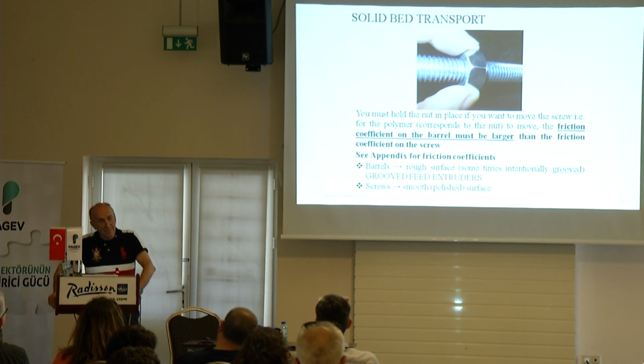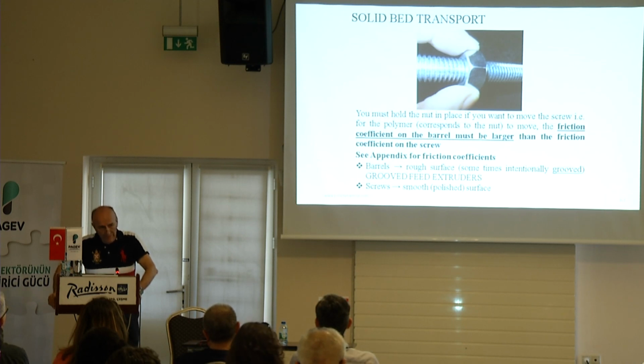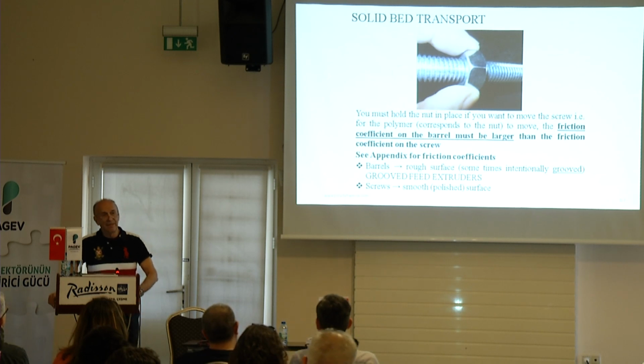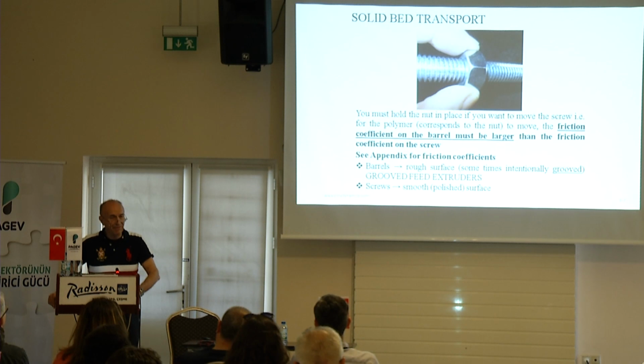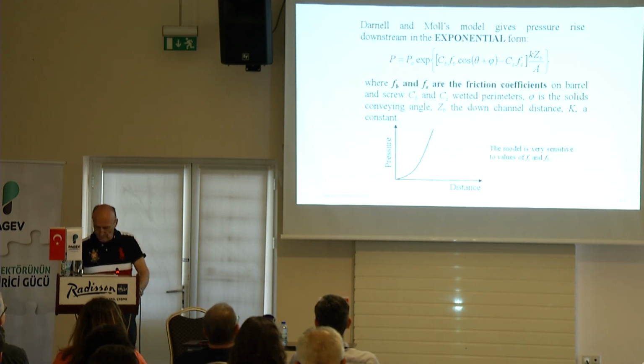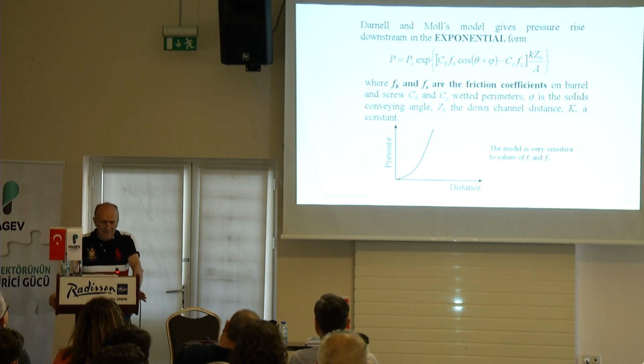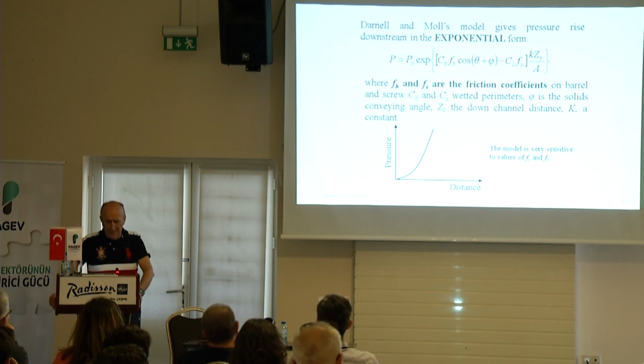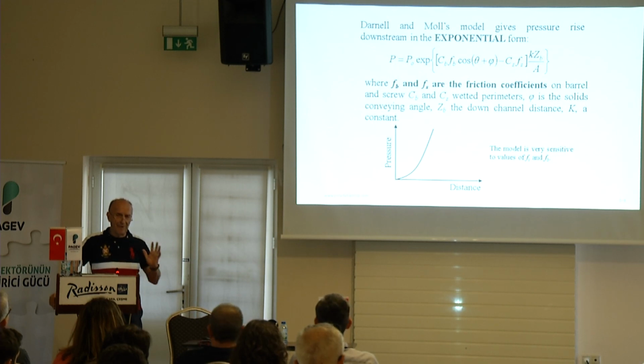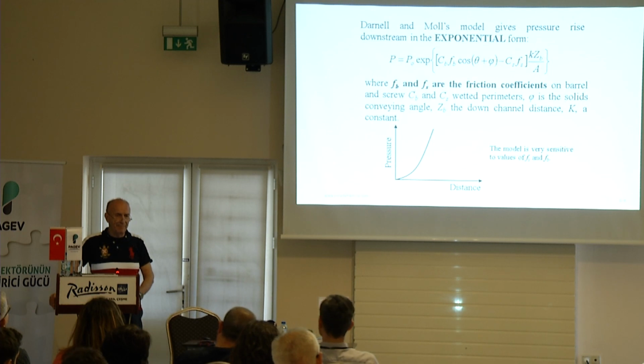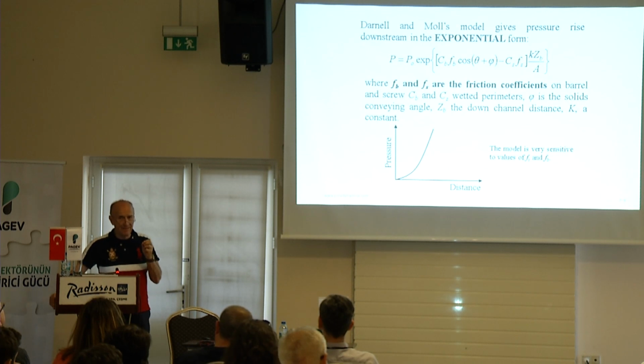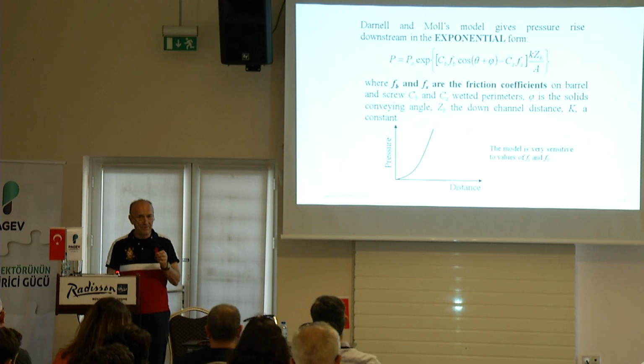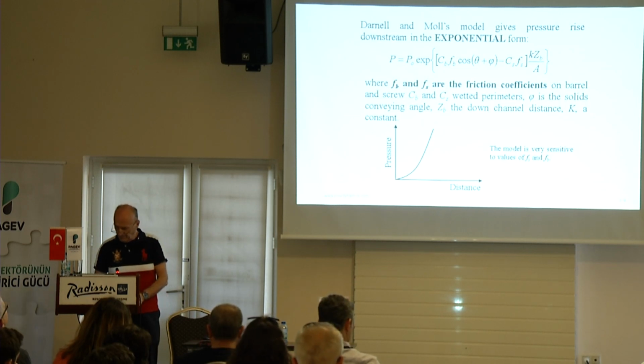In order for an extruder to operate and be capable of moving solid pellets forward, the friction coefficient between the solid pellets and the barrel must be higher than the friction coefficient between the solid pellets and the screw. Typically, I've written a couple of papers myself, other people have written more, and you see that this kind of mechanism with friction gives you an exponential pressure buildup. When you turn the screw, you build up a lot of pressure in a very, very short time.